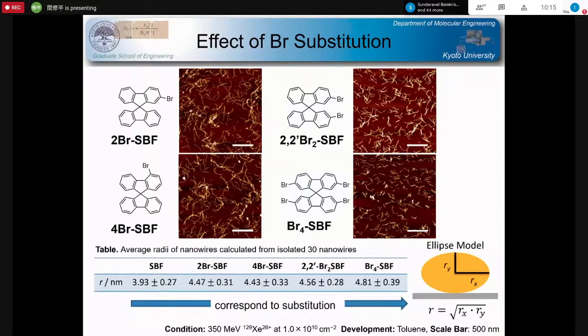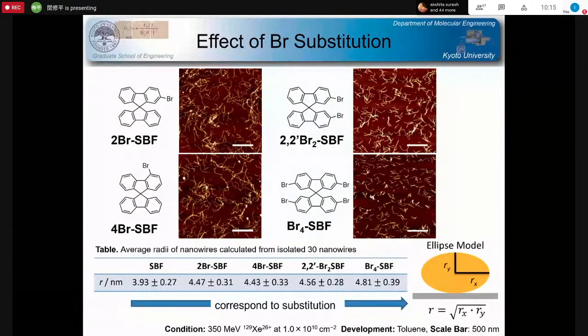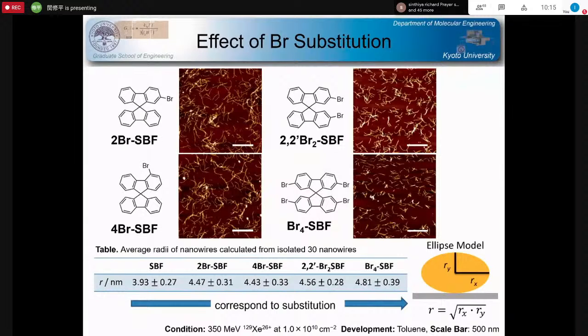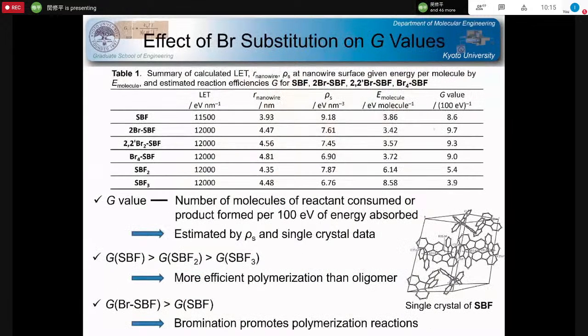As we expected here, in this case, highly efficient polymerization reaction, as well as crosslinking reactions, were promoted by the ion particle irradiation. And as in the previous cases, again, the halogenation also caused more efficient chemical reaction, giving thicker nanowires. So this type of chemical modification is also applicable to control the sizes of the one-dimensional nanowires by our technique. Okay, and this is a summary about chemical reaction efficiency.